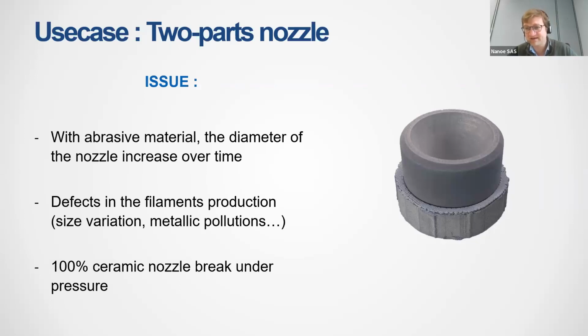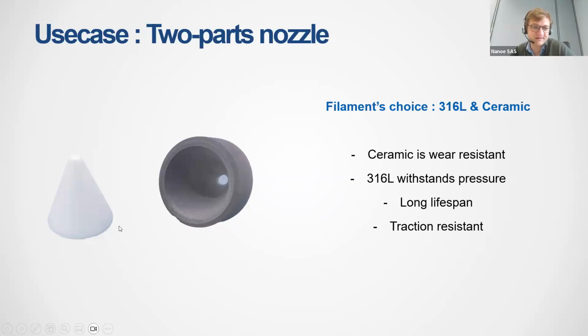So we had that idea of printing them in ceramic, of course, since we make ceramic filaments, but the problem was those ceramic parts used to break because there's a very significant pressure when we do extrusion. And so we ended up with a hybrid approach where we print the nozzle insert in ceramic and another shell in metal. You can see here the principle. You'll have an insert here, which is in ceramic, a conical insert that goes into this nozzle. That allows for wear resistance thanks to ceramic and to high pressure resistance thanks to 316L.